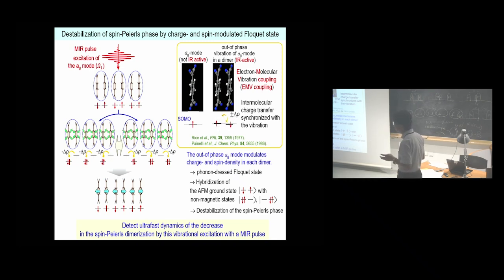This figure shows a totally symmetric intramolecular vibration, that is, an Ag mode. An Ag mode is not infrared active in isolated molecules. However, an Ag mode modulates the molecular orbital energy up and down like this. The out-of-phase vibration of the Ag mode induces intermolecular charge transfer synchronized with the vibration, and this mode becomes infrared active along this direction.